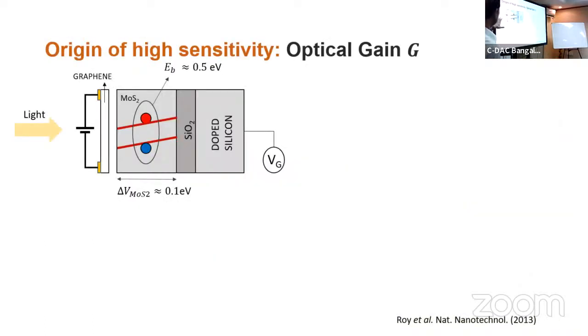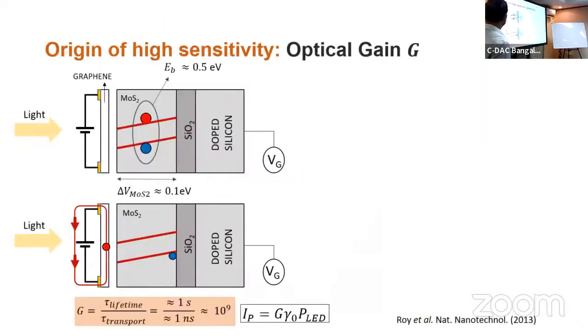So the basic science of it: the electron and hole pairs are generated when light falls on molybdenum disulfide, and then the electron jumps out, goes into the graphene layer, and gives you the current, but the hole stays back in the molybdenum disulfide and doesn't recombine ever. So as a result, this simple idea led to 10 billion times enhancement in the sensitivity to light.